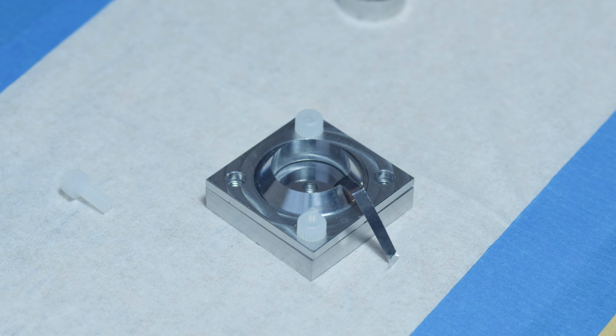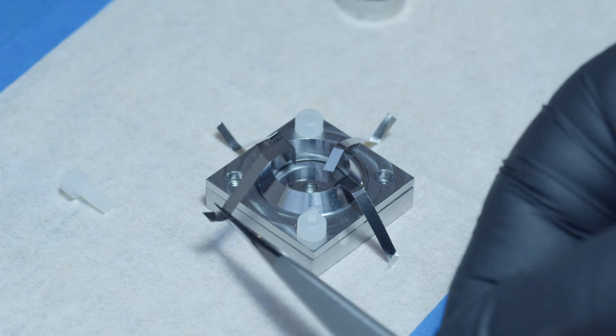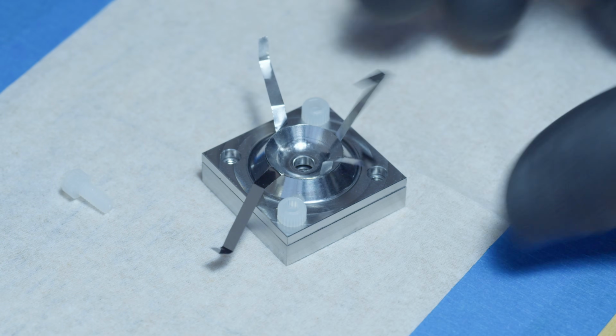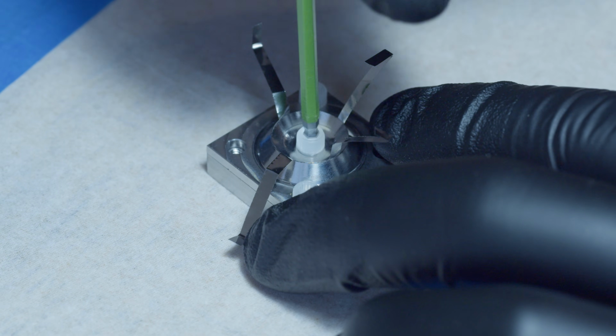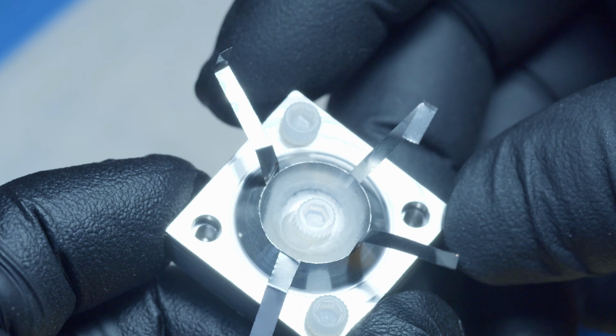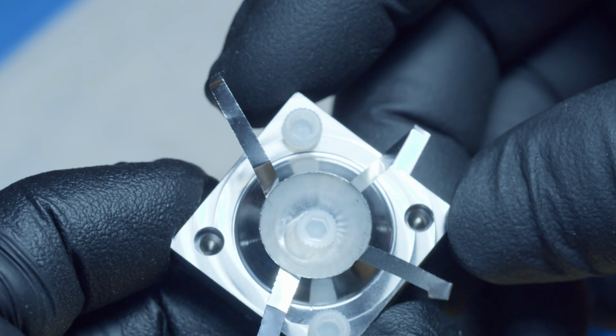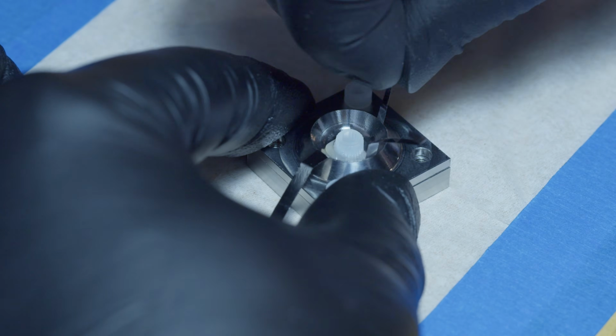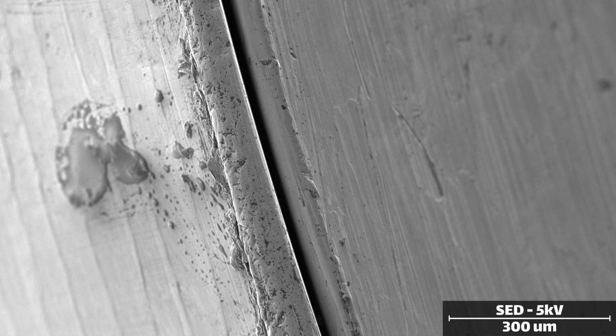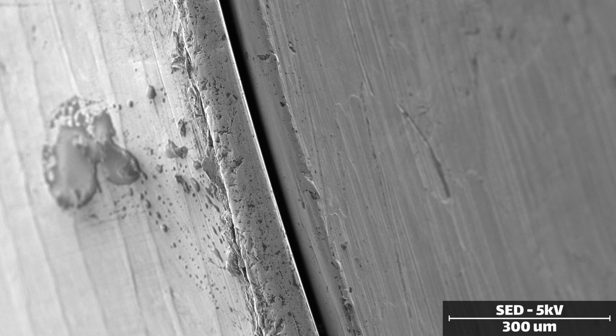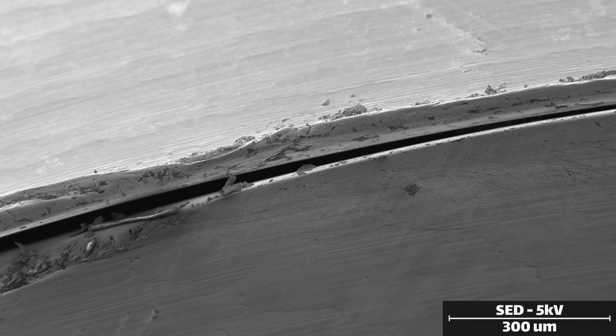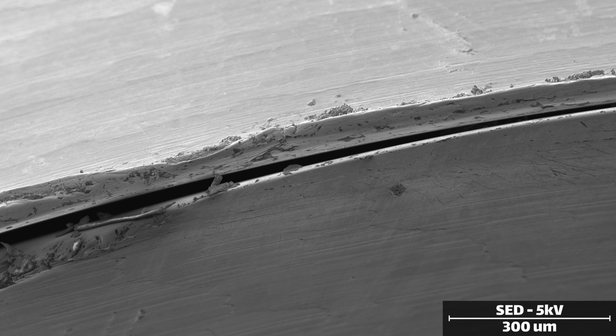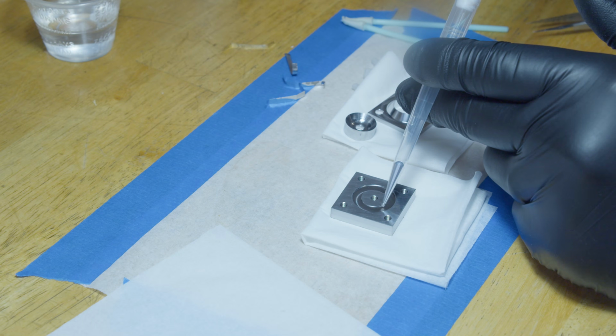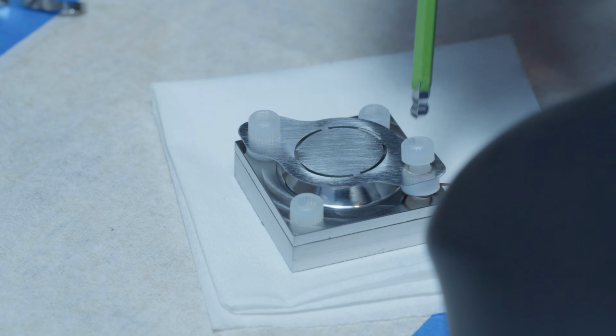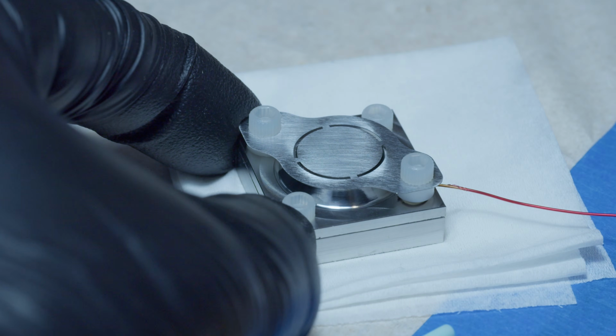The outer section is bolted down, precision shims are placed around the circumference, and then the inner section is secured in place. The shims are 12 microns thick, so in theory we should have an equal spacing all the way around. In practice, the slot varies a little due to manufacturing issues on my end. It ranges from 9 to about 30 microns depending on location, but I figured that's probably acceptable. Gallium is loaded into the reservoir at the base and then assembled with the electrode on top, and it's into the vacuum chamber for testing.